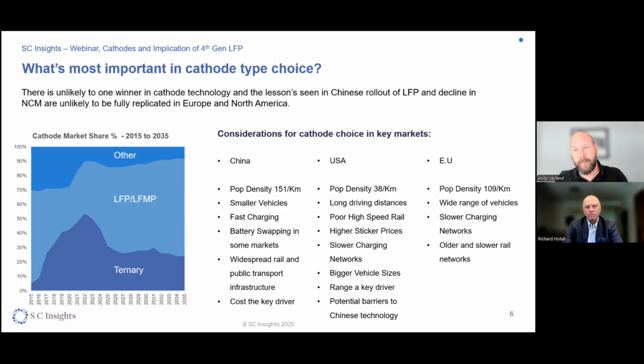We don't have any battery swapping infrastructure to speak of, whereas many Chinese cities do. With a much lower population density in North America, you don't have the high-speed rail network that China does. Charging infrastructure is typically much more dispersed, with far fewer units per number of vehicles, and also typically a lot slower. And that's not something which is going to change in 5 to 10 years. When you look at the amount of investment that's needed in grids, and the issues with putting new charging stations up, it's very different in China to Europe and North America.